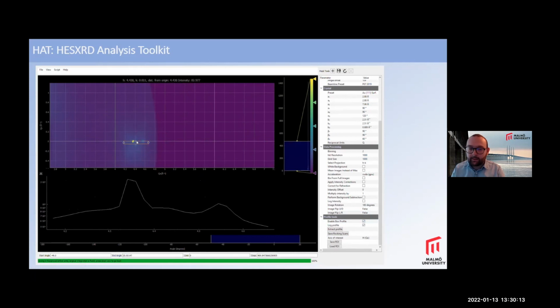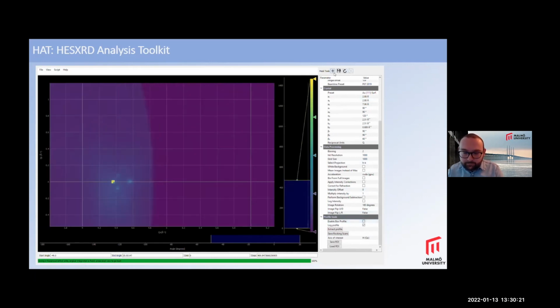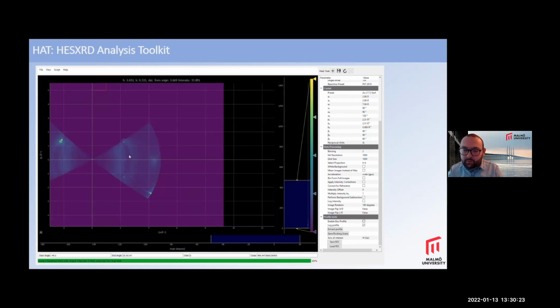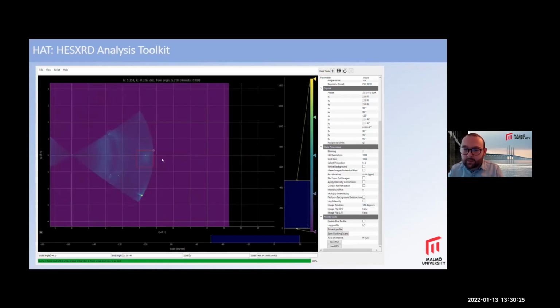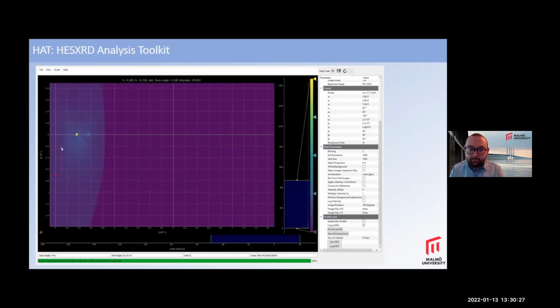So this is the higher order reconstruction, or the spots around one of the CTRs due to the reconstruction on the gold 111. You can also, if you want to extract CTRs, take a mask in the in-plane, and then you can project that on, say, the H and L plane, and you can use that to extract a CTR.